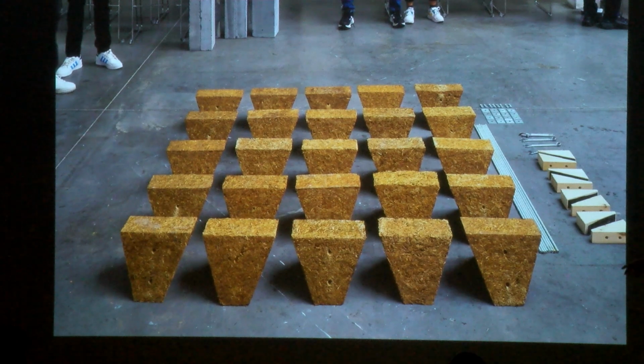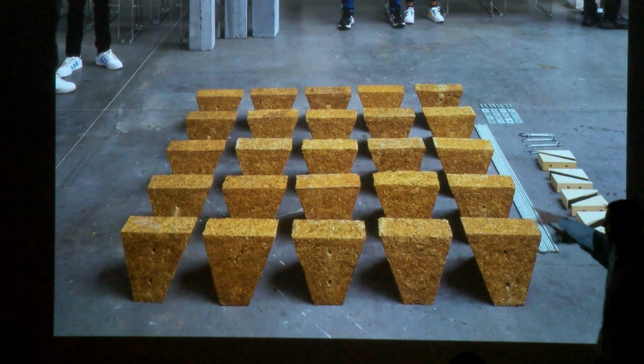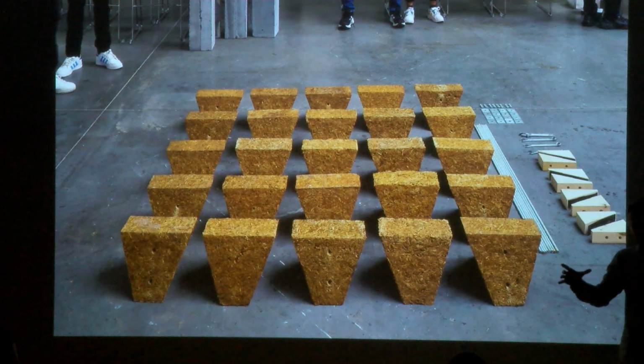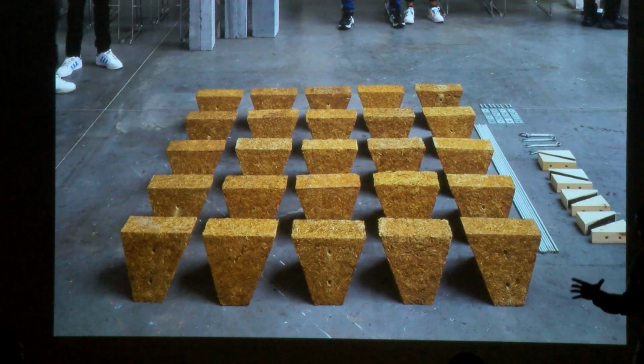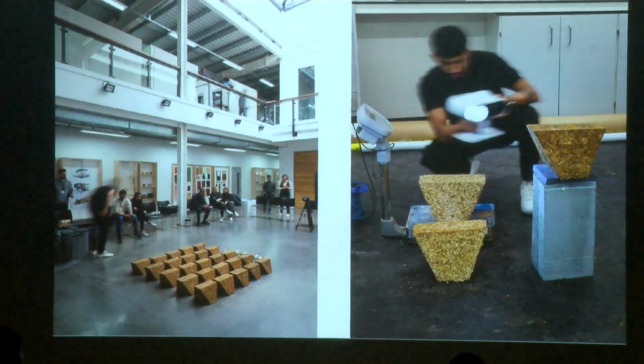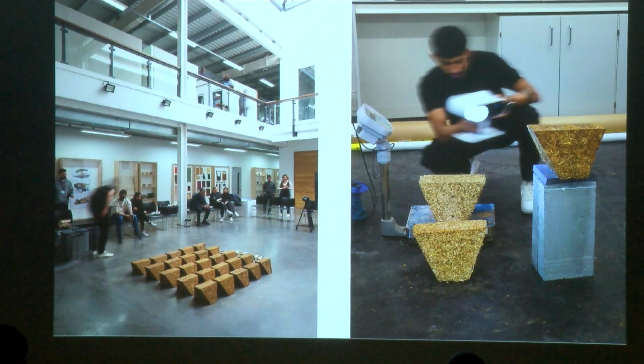For this initial prototype, we used metal rods on the perimeter, so the perimeter was working in post-tension. Once all the blocks were coming together, we were passing these rods on the perimeter, tying them on the ends, and then applying the right amount of pressure until the blocks were kept together, and then the slab could be lifted.